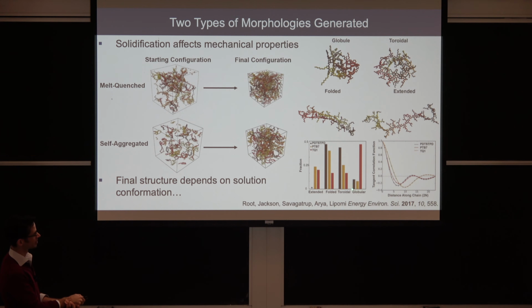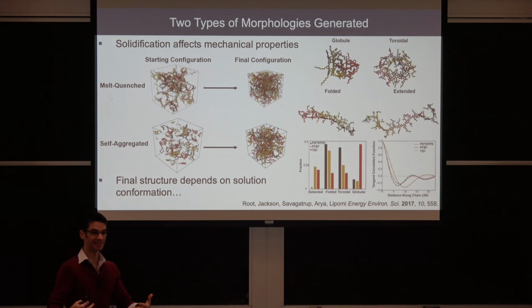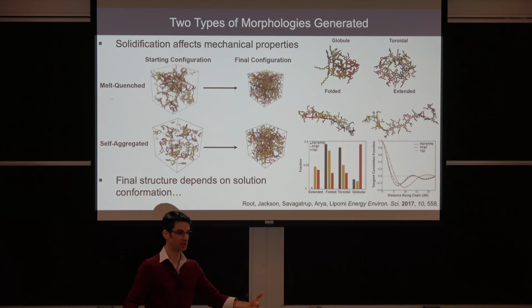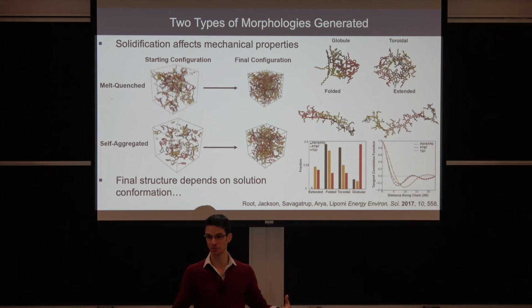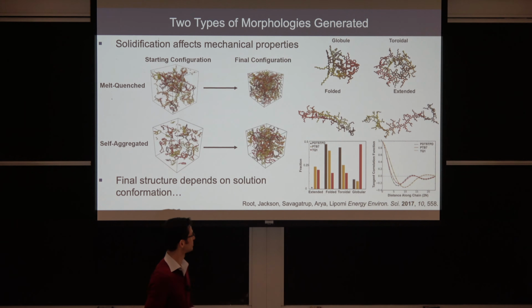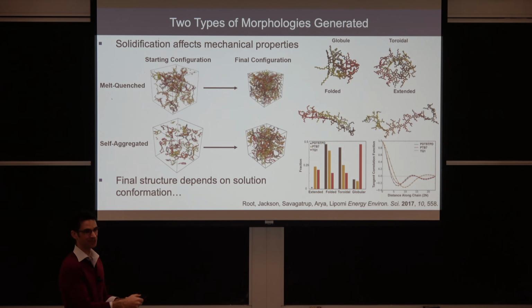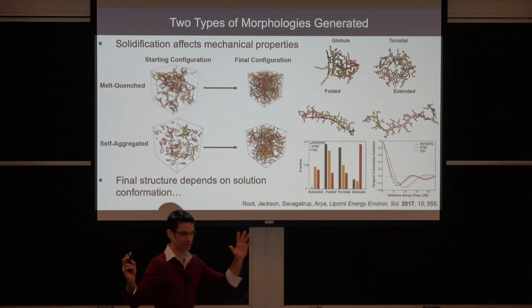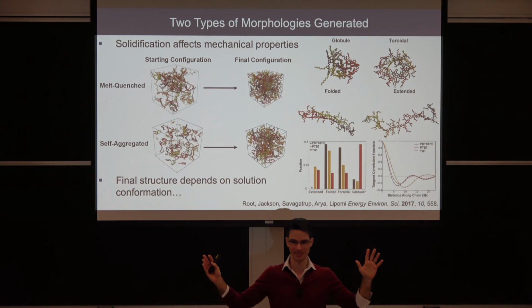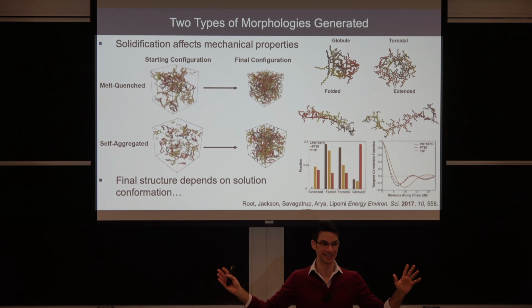So no surprise here, the globular morphology had a high proportion of TQ1, and TQ1 was the amorphous material, and we knew from X-ray diffraction experiments in the literature that it's relatively disordered. This is an interesting experiment here. Well, this is an interesting finding from the computation. This is called a tangent correlation function. So stay with me for a second, because it took me a long time to figure out what this actually meant when my student was explaining it to me.